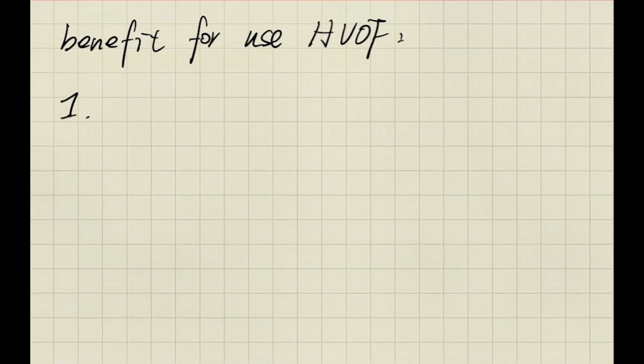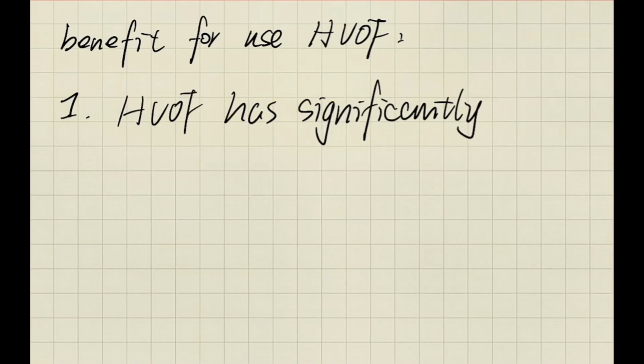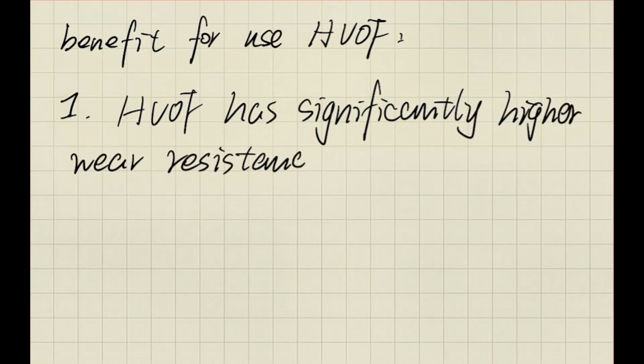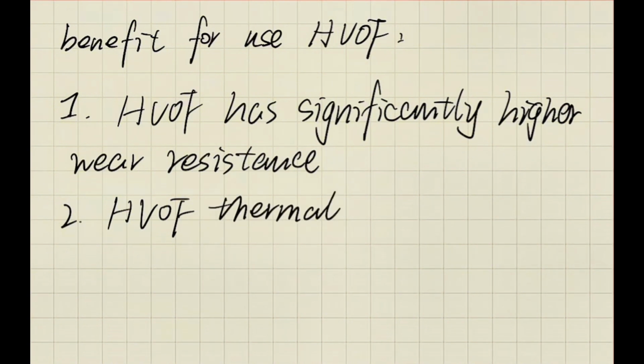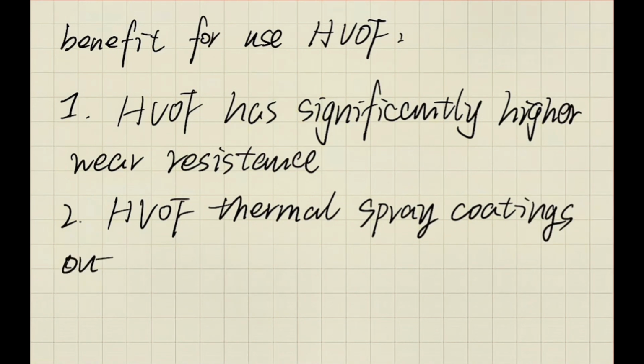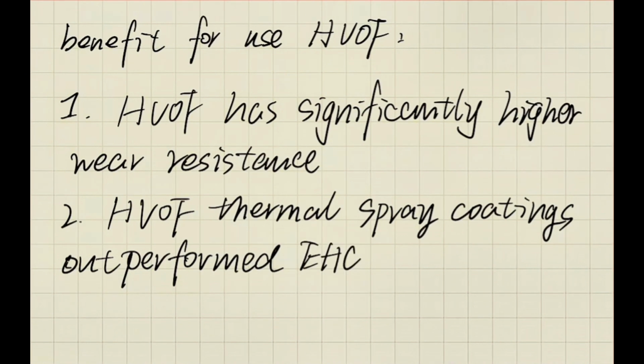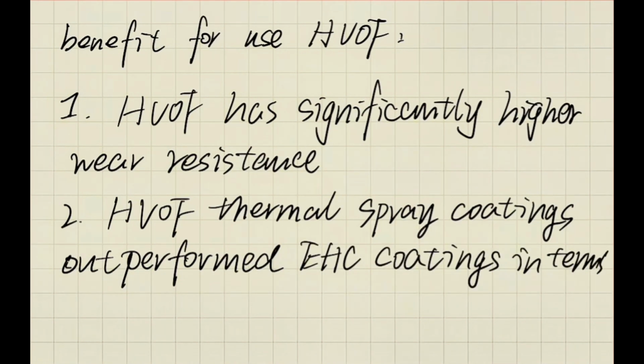There are many benefits of HVOF over EHC. First, HVOF has significantly higher wear resistance compared to EHC. In sliding wear tests, HVOF showed 200 times less material volumetric loss than EHC. It also demonstrated nearly 7 times less volumetric loss in abrasive wear tests.